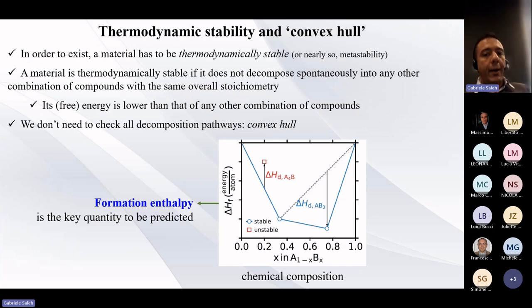As I said before, a material has to be thermodynamically stable to exist. There are cases of metastability in which a material is not quite thermodynamically stable, but in general, it has to be very close to thermodynamic stability to exist. Thermodynamic stability means that a material is thermodynamically stable if it does not decompose into any mixture of other compounds with the same stoichiometry. In other words, more rigorously, the free energy of the material has to be lower than the sum of any possible combination of other compounds or materials with the same stoichiometry.